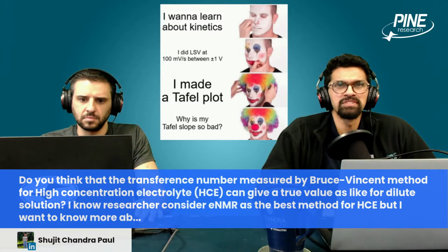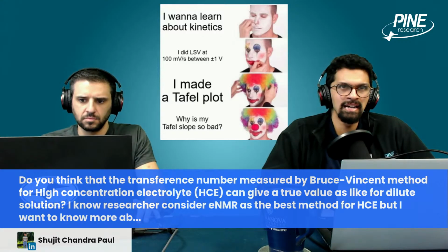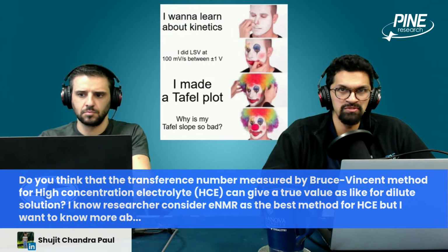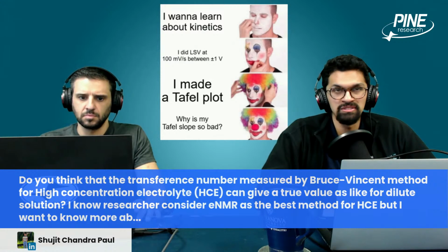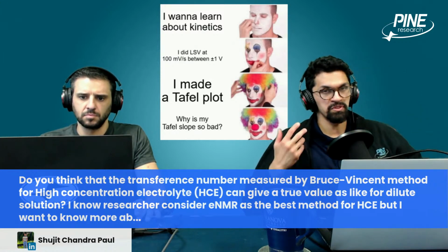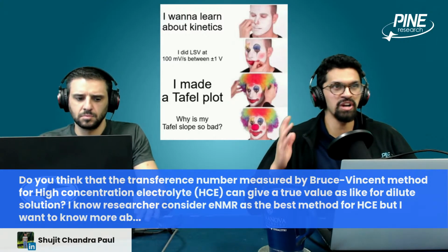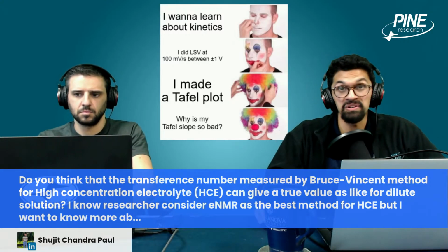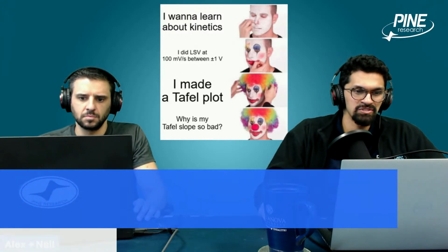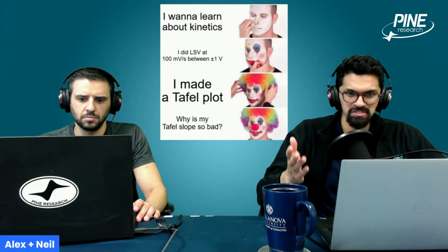I know we have the Bruce-Vincent method as a kind of combination of chronoamperometry and EIS and calculating some resistance values. Ultimately, you're trying to get the fraction of the current which ion is carrying, to get the transference number. I believe the Bruce-Vincent method will break down depending on the electrolyte concentration, if it's too high or too small.